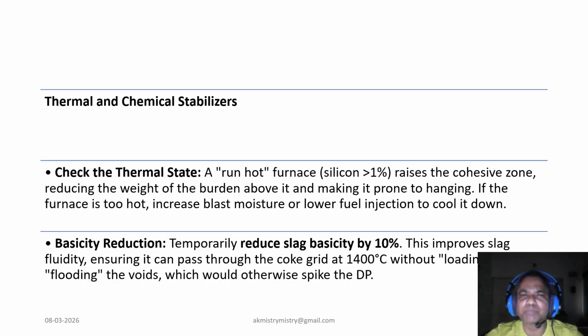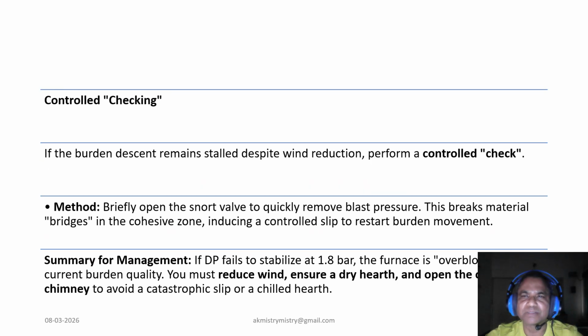So now if the burden is still stuck, you may need a control check by briefly opening the snort valve. You quickly remove pressure to break material bridges and induce a controlled slip to restart the movement. Finally, remember the safety limit. If dp stays above 1.8, the furnace is overblown. You must reduce wind and fix your burden quality to avoid a catastrophic slip or a chilled hearth.